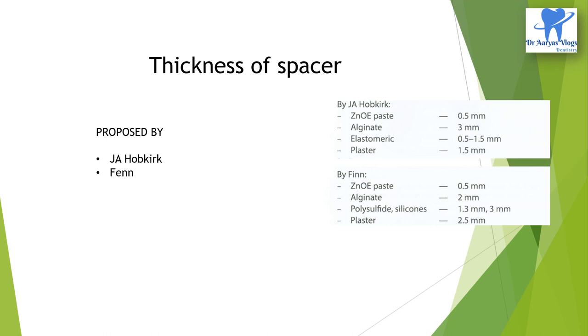mm. And by Fenn, zinc oxide eugenol paste is 0.5 mm, the same as Hobkirk, but alginate is 2 mm only. According to Hobkirk, 3 mm is needed, but by Fenn, alginate only 2 mm. Then elastomeric is 0.5 to 1.5, and by Fenn, 1.3 mm. And plaster is 1.5 by Hobkirk and by Fenn, 2.5. So these are the various thicknesses of spacer.